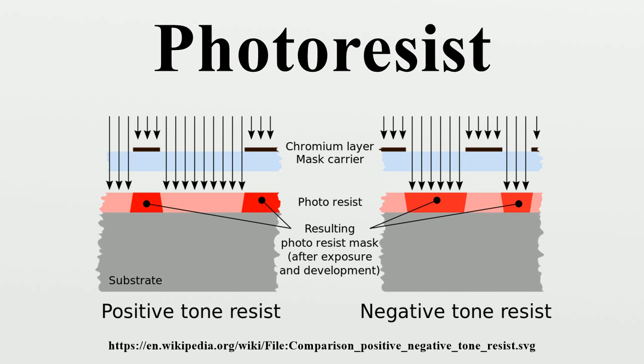Other aspects of photoresist technologies — Absorption at UV and shorter wavelengths: Photoresists are most commonly used at wavelengths in the ultraviolet spectrum or shorter. For example, diazonaphthoquinone absorbs strongly from approximately 300 nm to 450 nm. The absorption bands can be assigned to n-π* and π-π* transitions in the DNQ molecule. In the deep ultraviolet spectrum, the π-π* electronic transition in benzene or carbon double-bond chromophores appears at around 200 nm. Due to more possible absorption transitions involving larger energy differences, the absorption tends to increase with shorter wavelength or larger photon energy.